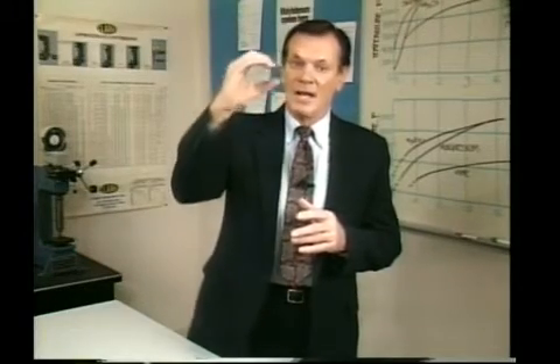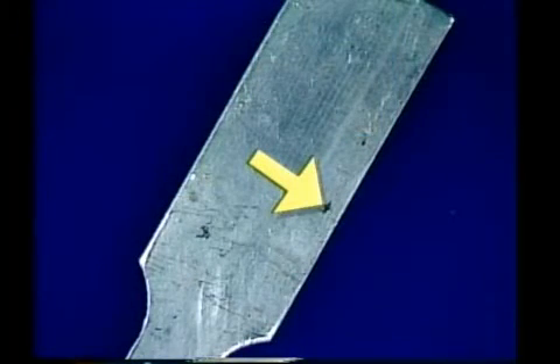If the gaseous hydrogen forms at a discontinuity near the surface and expands, a surface bubble occurs. The hydrogen can also collect at discontinuities below the surface, thereby causing subsurface voids or crevices within the metal, which are not visible on the surface. Subsurface HTO can only be observed by metallographic examination. Some examples of blisters and HTO occurring on a 2014 forging are shown in this illustration.